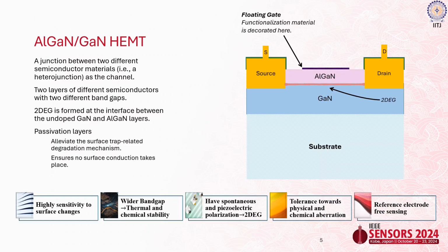So our solution is to overcome these problems using AlGaN GaN HEMT. So it is simply a junction between two different semiconductor materials, that is the heterojunction that is working as the channel. So these two semiconductors having two different band gaps and a 2D electron gas is formed at the interface between the undoped GaN and the AlGaN layer. So if you see between the AlGaN and GaN, at the interface, a sheet of charge forms.